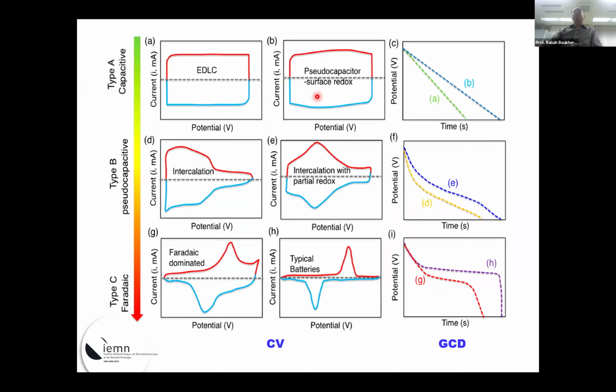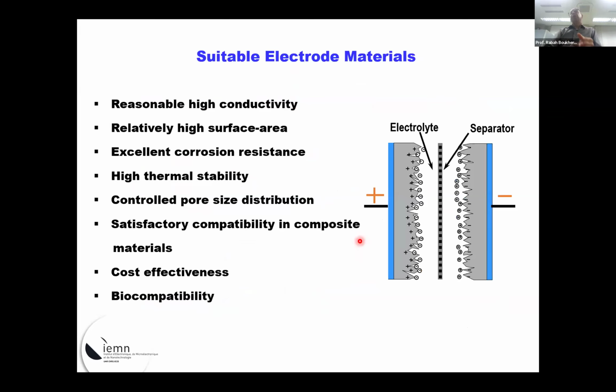If you have some pseudocapacitive behavior, then you still have this rectangular shape with some contribution from the Faradaic reactions. And from the galvanostatic charge discharge, you have very nice linear curves. Ideally, if you have a pure EDLC, you will have this linear shape of your GCD. You see there's a difference if you have a pseudocapacitive or a Faradaic material, between the two from the GCD, but also from the CV. So this is just to give you an overview, when you do the CV or the GCD, of what type of behavior you would expect from the electrochemical characterization.